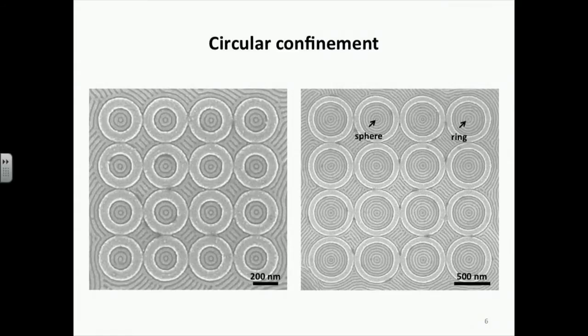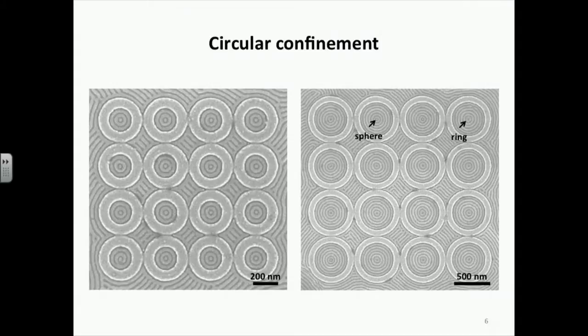We first tried circular confinement. As expected, we observed well-ordered concentric ring shapes. In the left SEM image, we can observe two concentric rings with a center sphere. In the right SEM image, we can observe five or six concentric rings with a center sphere. Both patterns are observed in the same template because the equilibrium periodicity L0 can vary between 35 and 39 nanometers.